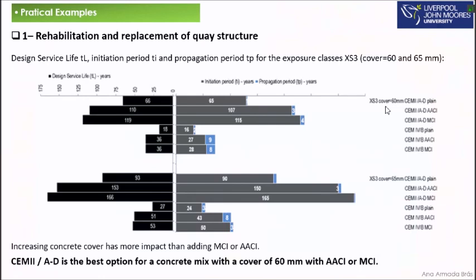Okay, so you have the same here, but with the concrete cover of 65. Basically, increasing the concrete cover has more impact than adding an MCI or an AACI. So we should take that into consideration sometimes. As you can see, there is an increase of service life if we increase the concrete cover. However, cement type 3 with AACI is the best option for a concrete mix with a cover of 60 millimeters, and with AACI corrosion inhibitors or MCI type. What you can observe from this is that the main contribution is for the initiation period, not for the propagation period.